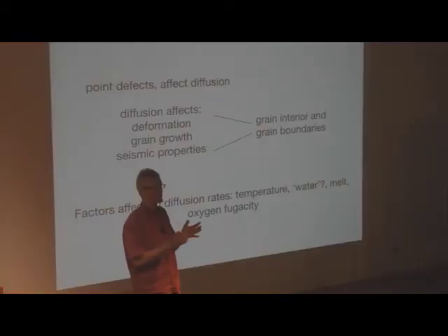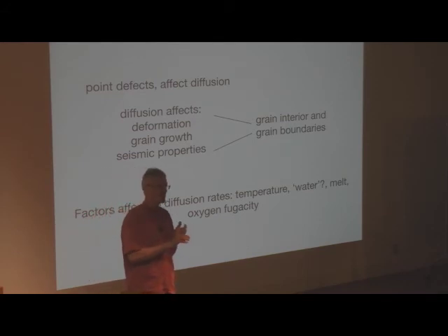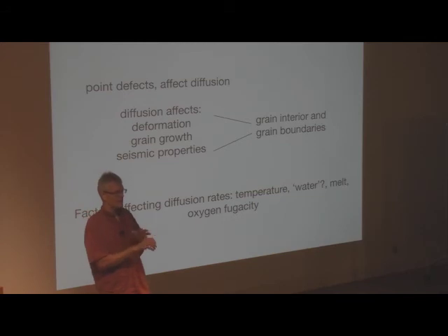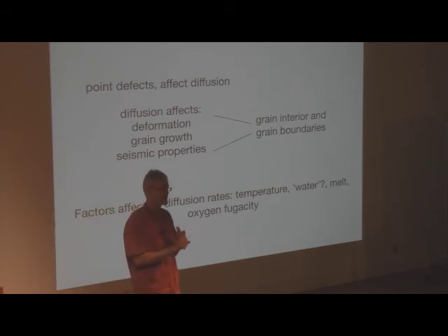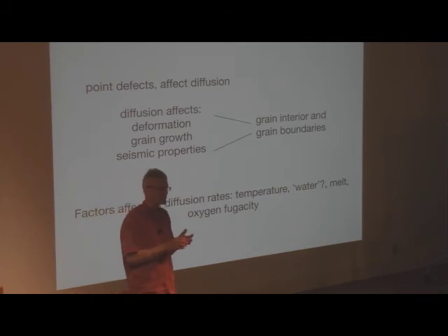There is a sensitivity to oxygen fugacity, but for example, wet forsterite, under the same conditions at high oxygen fugacity, behaves like dry FO90 olivine. So you can have high oxygen fugacity, high water content, and it doesn't make a difference on the physical properties. And there are similar things. There are papers that look at diffusion in pure forsterite that also find essentially that water has no effect in pure forsterite.